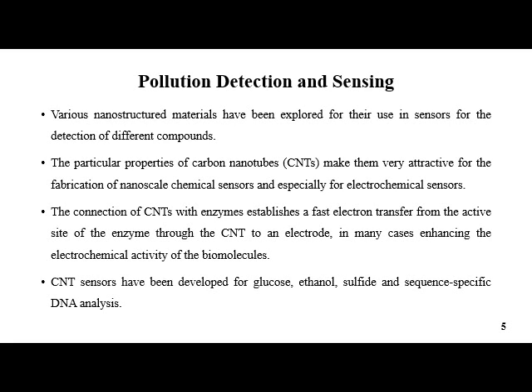The bottom-up fabrication approach makes CNT fabrication compatible with silicon microfabrication processes. The connection of CNTs with enzymes establishes fast electron transfer from the active site of the enzyme through the CNT to an electrode, enhancing the electrochemical activity of biomolecules. To take advantage of CNT properties, they need to be properly functionalized and immobilized.